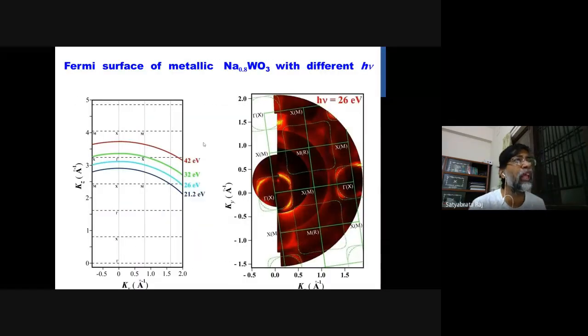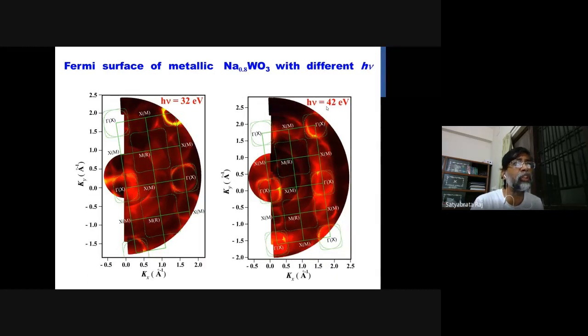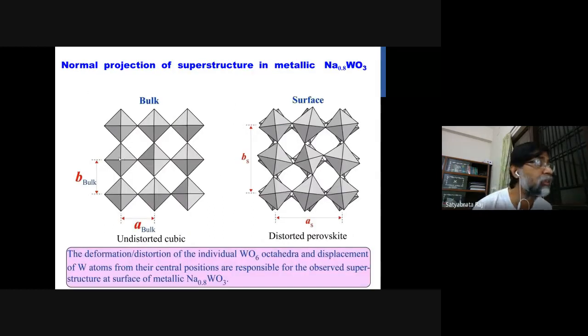And if you take a 26, you still don't see any Fermi surface around MR point. But if you see a 42, which is surface, you can see in the gamma, in the X point, the Fermi surface is appearing. What does it mean? That means in the bulk, you have an undistorted cubic structure, and this is the cubic structure. But in the surface, you have a distorted WO6 octahedral, which makes this a distorted perovskite type of structure.